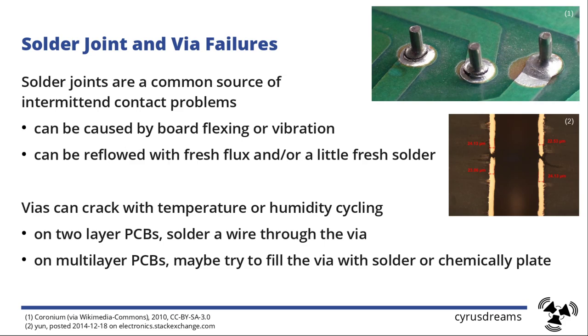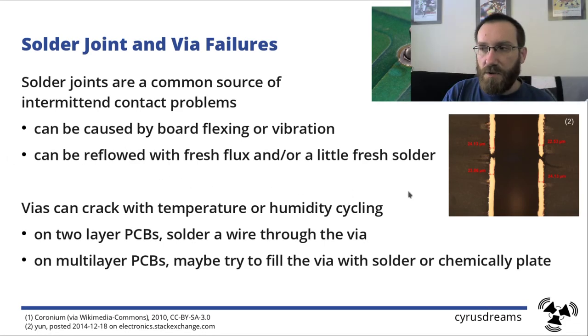A far more annoying failure that you can have on a PCB is if the via that connects from the bottom to the top side is cracked in the middle. You cannot see that because it's inside the PCB, but there's no top to bottom connection anymore. Very hard to find. Sometimes it's even dependent on the temperature where you measure the board. So you have something that works at room temperature, and if it gets hot, it always shuts down.